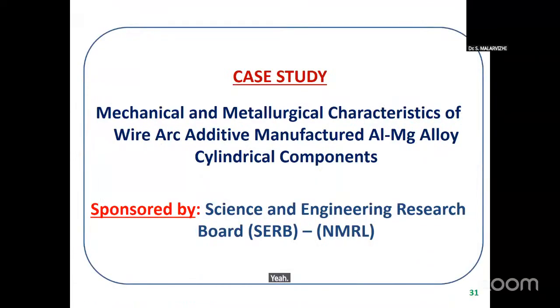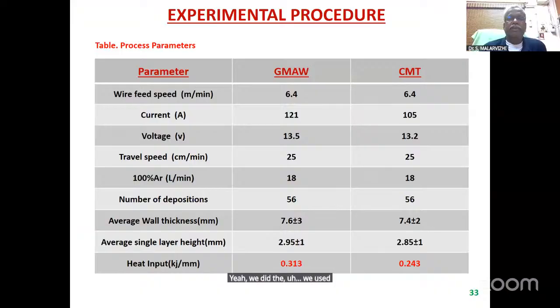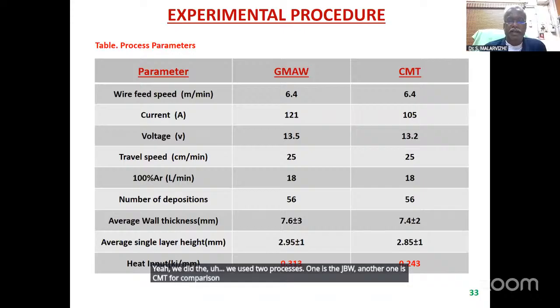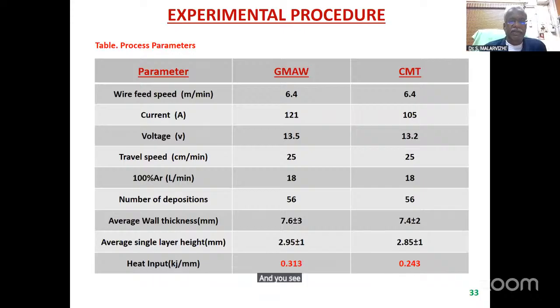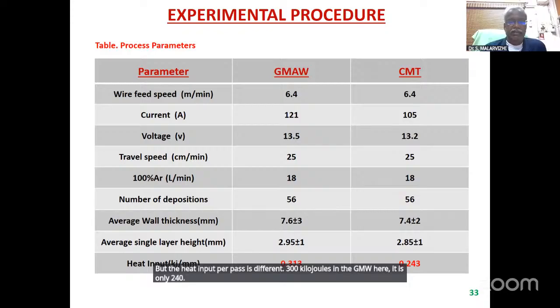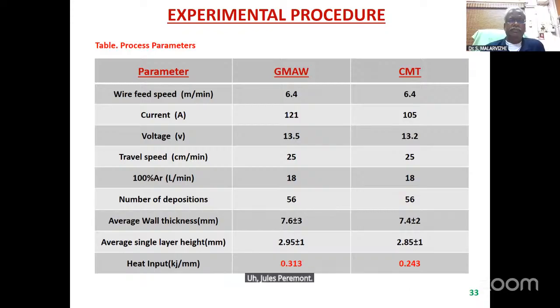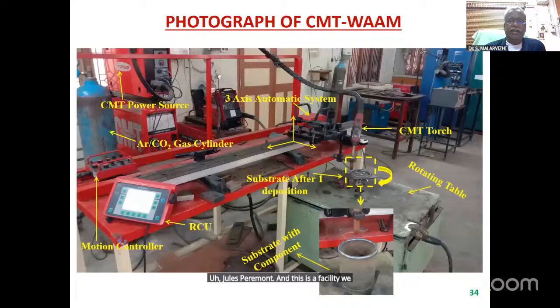We used two processes, one is GMAW and the other one is CMT, for comparison purposes. The number of depositions to achieve 150 mm height is 56 in GMAW and 56 passes in the CMT process. The number of passes remains the same, but the heat input per pass is different. It is 300 joules per mm in GMAW, and here it is only 240 joules per mm. This is the facility we used, and these are the cylinders we made.